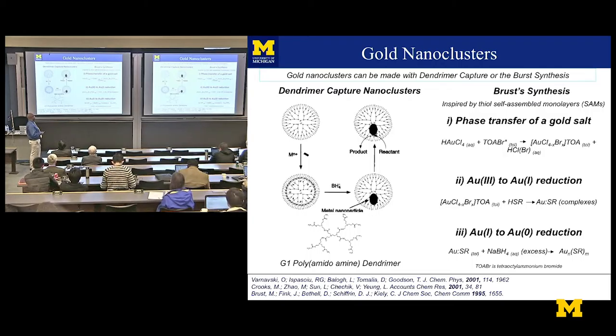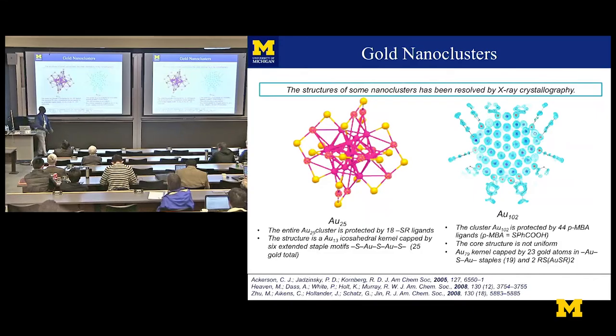Now, this looks very straightforward. Yes, there are some details about how long you wait and so on, okay? Wait too long and it decomposes and so on. This actually is a very stable material if you isolate the system and mass spec it. Another group has shown that you can do this inside dendrimers as well. But the main point is that with these syntheses now, it is a pretty foregone conclusion that people can make gold clusters in their laboratory. In fact, even high school students in the summer can make them. That's a big deal, okay? It's a big deal that high school students can make them, but it's also that they can make it in the summer.